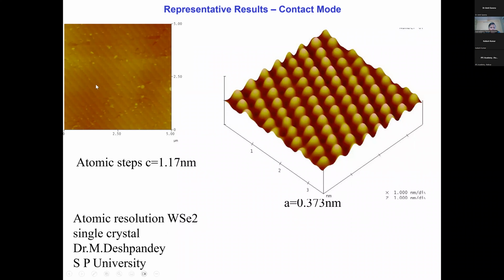Now, in this one of the small ones, this width is about 5 micron. This is about 10 to 20 steps. Therefore, it will be around 250 to 500 nanometer width, each step width. You go and sit, it's a big 250 nanometer, so big. You go and sit your tip here and focus it to a very high resolution.